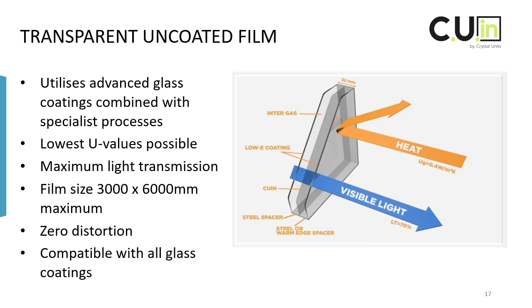Because transparent uncoated film utilizes advanced architectural glass coatings, combined with specialist factory processes, the lowest U values are possible, meaning there is less heat loss and less waste. It does this while maintaining maximum light transmission with very low levels of solar heat gain. Transparent uncoated films are not limited to the size of the magnetron coater, so the maximum size is currently 3000 by 6000 mm as standard. Minimal absorption of the sun's shortwave radiation means zero distortion over time.